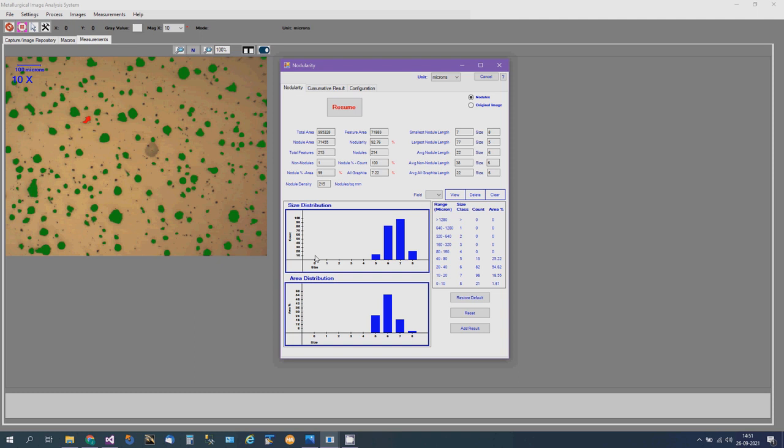So the system, based on the cutoff, if you look at the image, you can see that all these smaller things are not even considered because they all have a size less than 10% of the largest nodule. This one was eliminated because, if you see, C is the circularity. Circularity is 0.49. We have put a cutoff of 0.5. So that way we eliminate noises and shapes that are not really nodules.